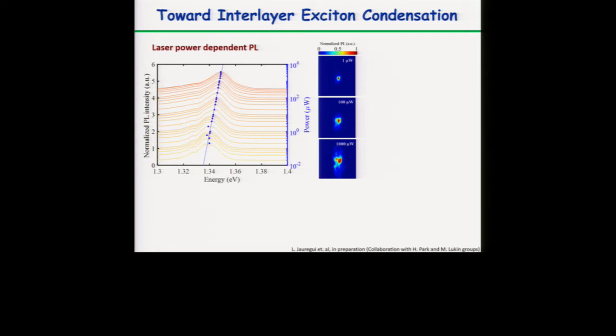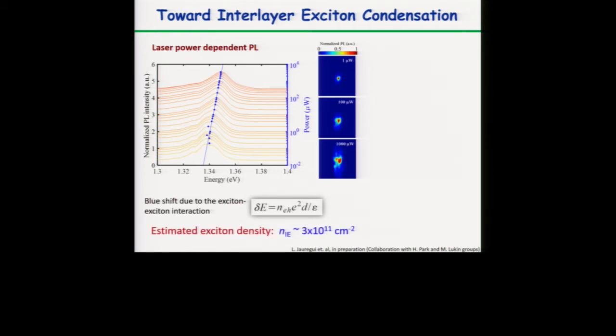Okay, if we do a power dependence now, we're collecting from the same spot as the excitation. In the power dependence of PL, what we observe is that the peak position in energy for the interlayer exciton shifts with power. At least for this spot and this laser power, we obtain a shift of around 10 millielectron volts. If we assume they are a parallel plate capacitor, based on this blue shift with power, we can roughly estimate the interlayer exciton density, and it's around 10^10.